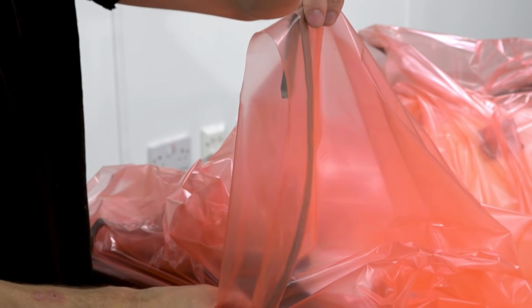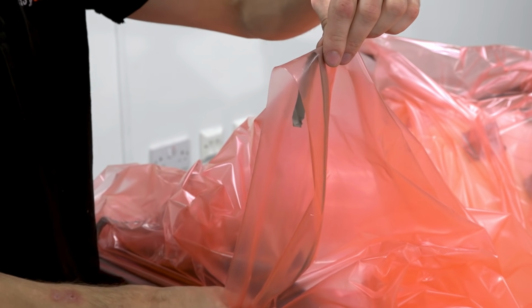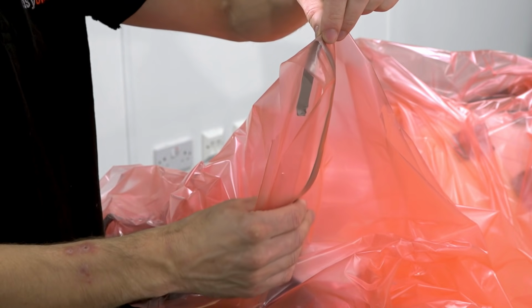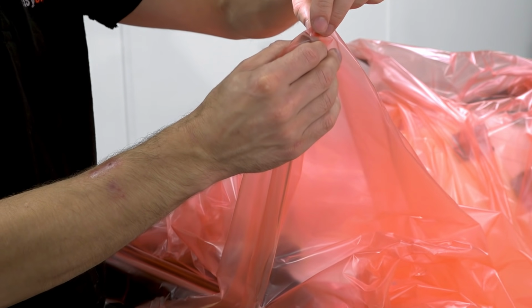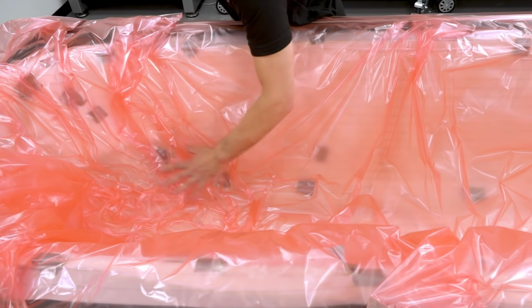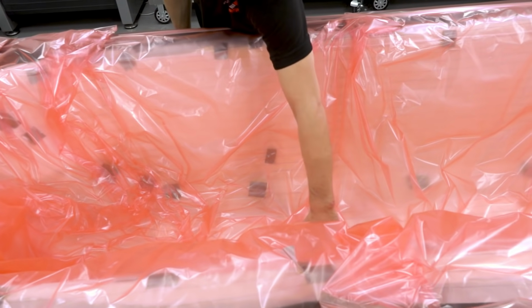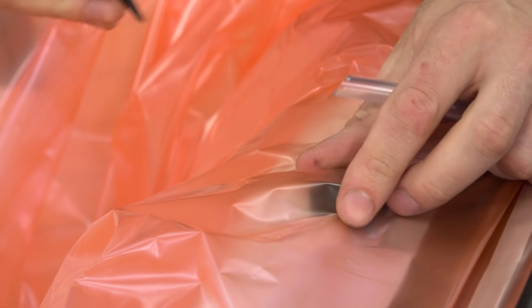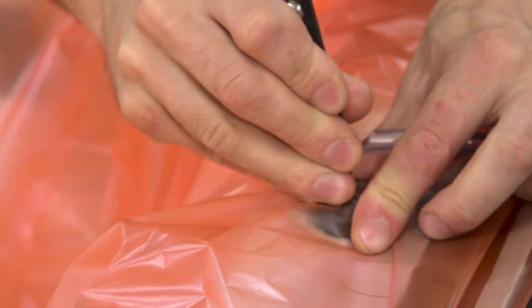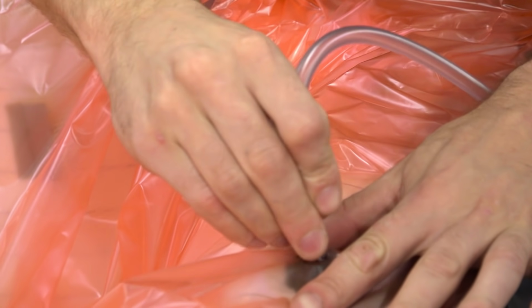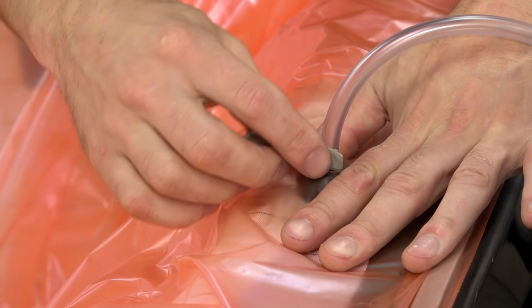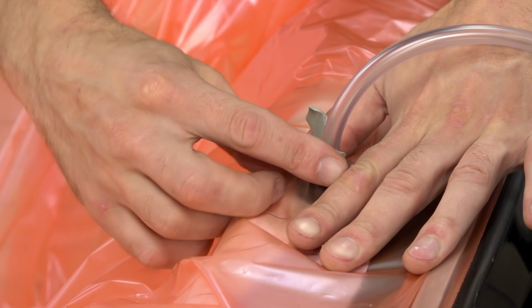Unless you've been lucky and have managed to keep the vacuum bag perfectly square throughout the sealing process, it's likely that you will either need to extend or reduce the size of the final pleat. The hoses can now be connected. This is simply a case of piercing the bag, pushing the hose through and sealing with sealant tape, ensuring that the bag has no creases under the seal.